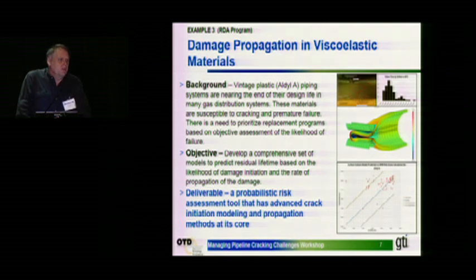It is also very similar to the previous project I talked about in that here we're talking about true viscoelastic damage initiation and propagation, which is very similar to the elastic plastic with strain hardening models we talked about earlier. So there's probably about 85% overlap between this and a true steel project. And the really interesting portion of it is the plot on the bottom right-hand corner, where we're predicting lifetime of a pipeline based on a lot of different attributes that we're pulling in, and we're getting pretty good agreement. So this is a very good example of how to address the problem of data integration, of looking at more than just what's straight in front of your nose.